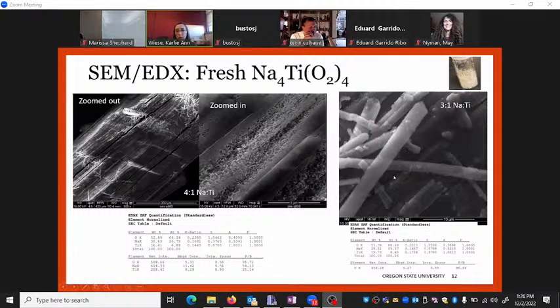And then notice that there were some other crystals that looked a little bit different in appearance. So we zoomed in on that region and saw that there's a slightly different ratio, 3:1 sodium to titanium ratio. So we do have some other phase in smaller quantities present within our sample as well.